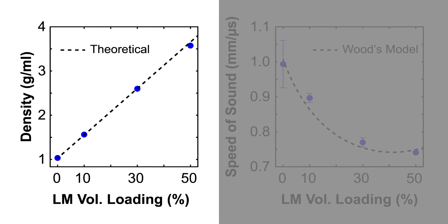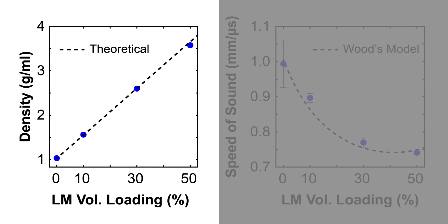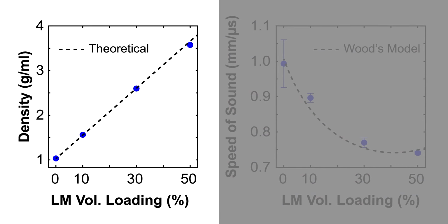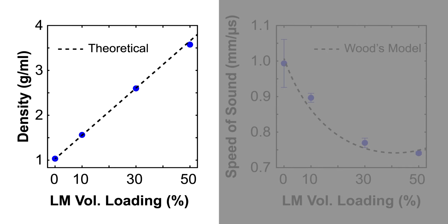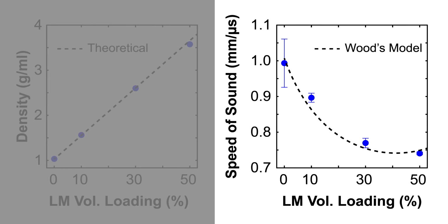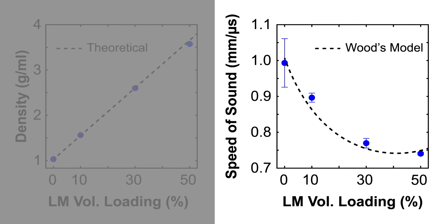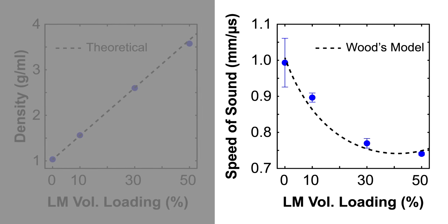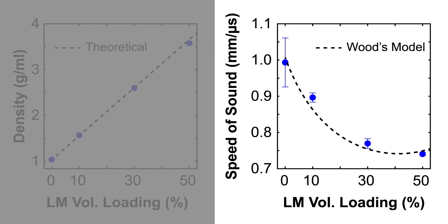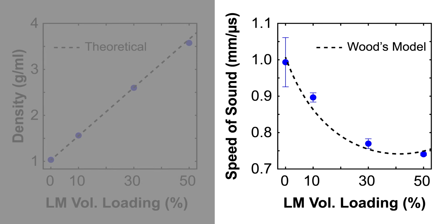Here you can see that as the loading of liquid metal in the elastomer is increased up to 50% by volume, the density of the composite increases linearly, and the speed of sound through the material decreases. The decrease in the speed of sound is expected and can be predicted by the Woods model as indicated by the dashed line. The acoustic impedance is the product of the material density and the speed of sound through the material, which is shown to increase with liquid metal loading.